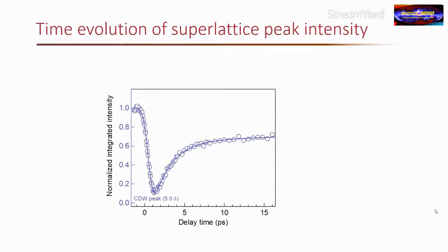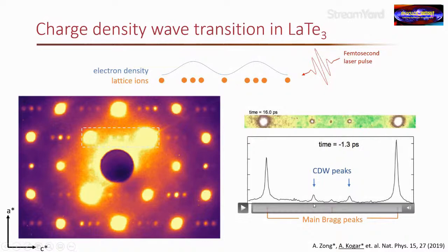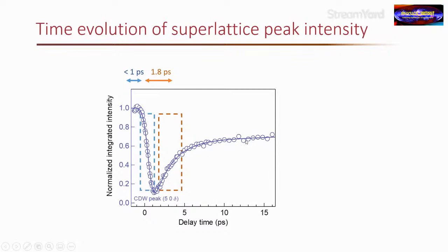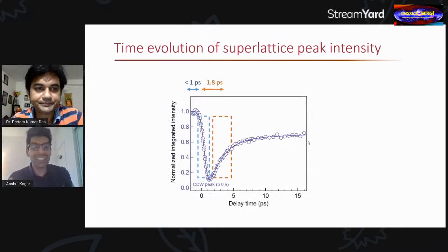We can be more quantitative: the peak intensity of the charge density wave suddenly decreases and then recovers. It takes less than one picosecond for the peak to decrease in intensity, and roughly two picoseconds to recover back to quasi-equilibrium. The reason the peak doesn't return all the way to its original intensity is that the laser pulse also dumps heat into the system, and as the system heats up, the peak intensity decreases slightly.